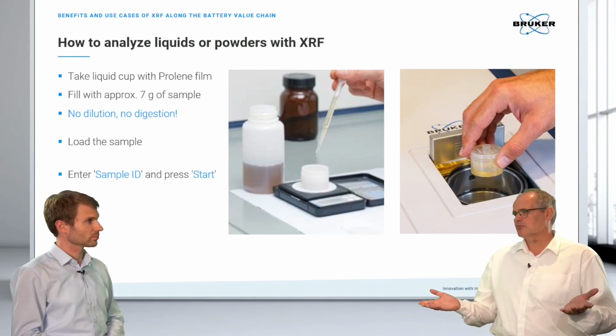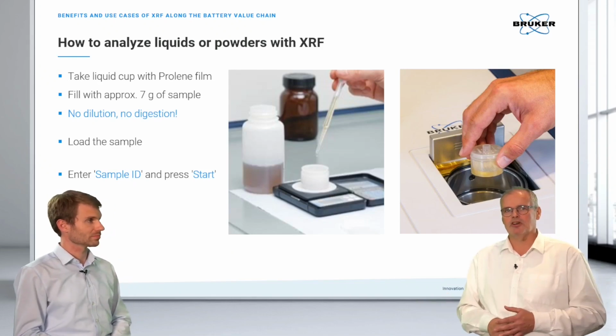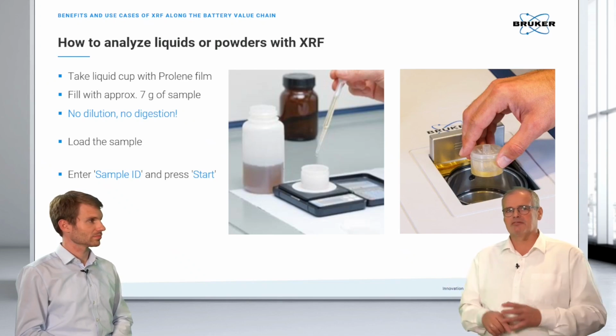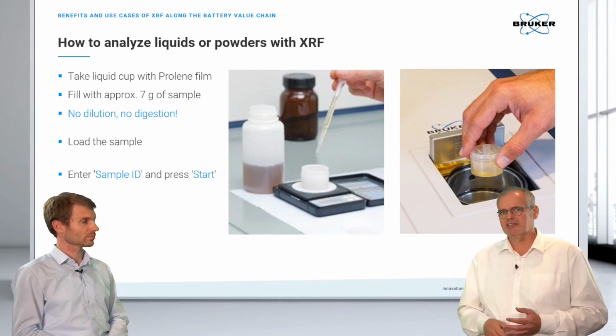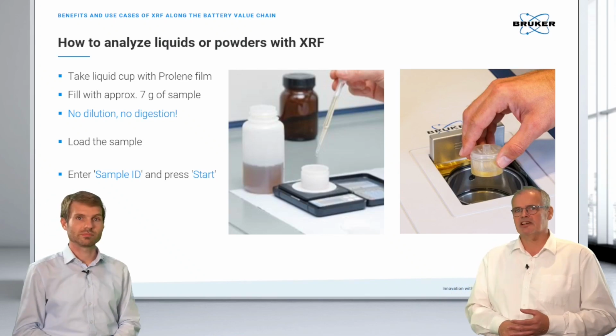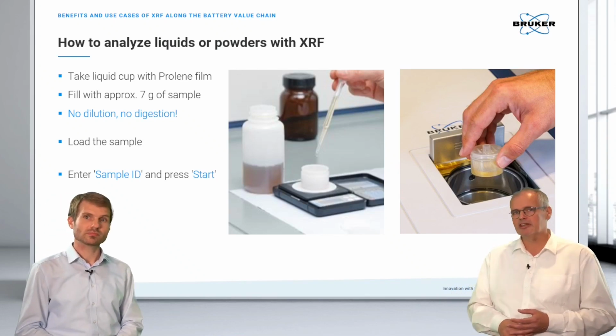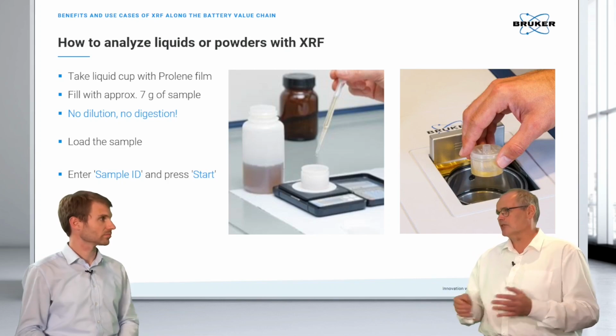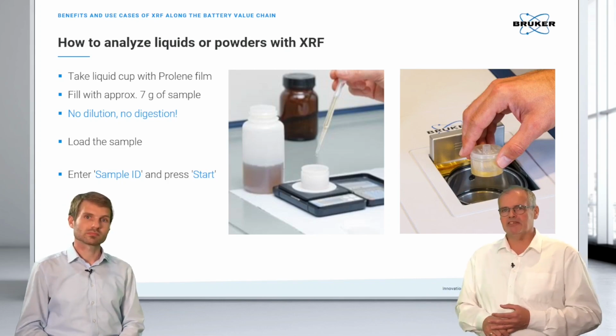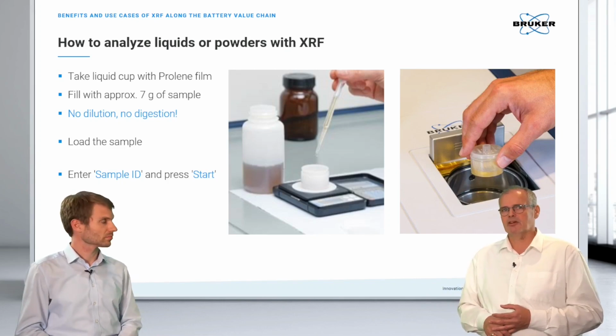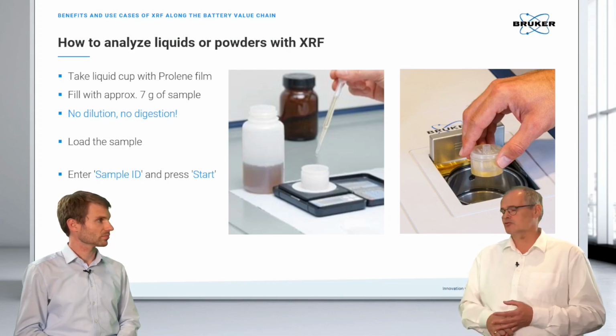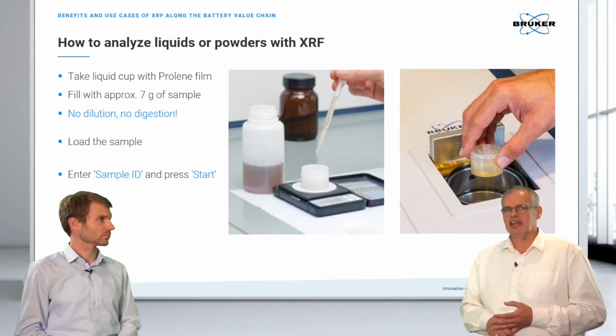You simply put the sample cup on a balance and fill in about 7 grams per sample. You see here on the right-hand side the picture of the manual loading. That's the easiest way when you have a few samples per day. This would be sufficient.